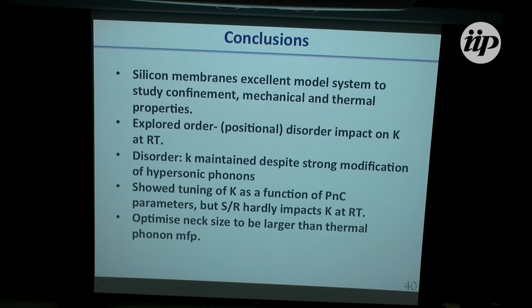So let me conclude. First of all, as stated before, the silicon membranes are a very good system to study not only confinement, but also mechanical and thermal properties, and decoupling in particular between optical and mechanical modes. We have explored order and the impact on thermal conductivity. We found that there is no impact of positional order on the thermal conductivity in the size regime where we have worked. We found that there is a way to tune the thermal conductivity in terms of the phononic parameters. Surface to volume ratio has an impact, but depends on the geometry.